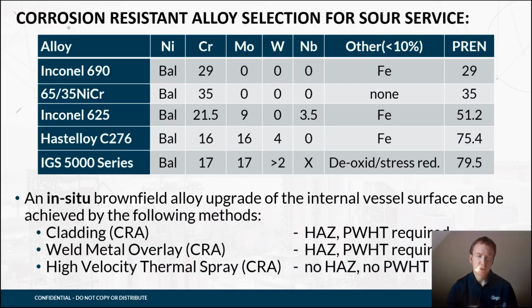So one of the first things we consider is what alloy we're going to install that is going to be suitable for the different environments we see in amine systems. We look at the different alloys in the marketplace, and what comes to mind is a C276 or a Hastelloy based alloy, which has a very high pitting resistance equivalent number, high resistance to these operating environments, and is going to be effectively inert or non-reactive. Once we've selected that alloy, then we need to think about how do we install that in the field? How do we get that put into our vessel during a shutdown and turnaround?